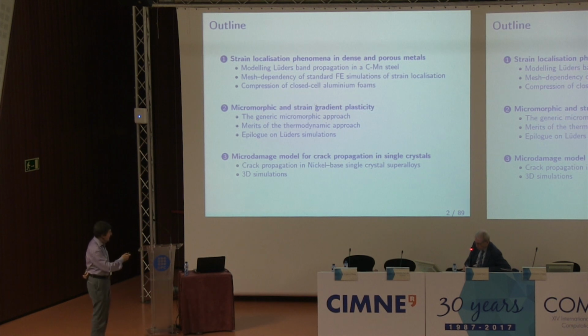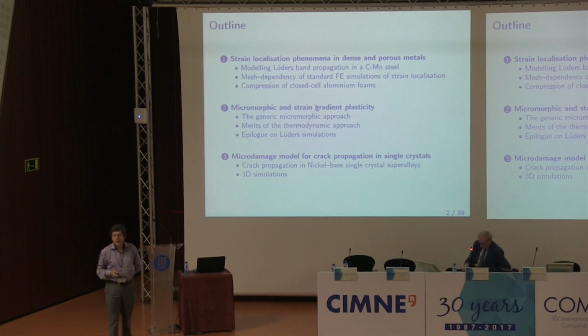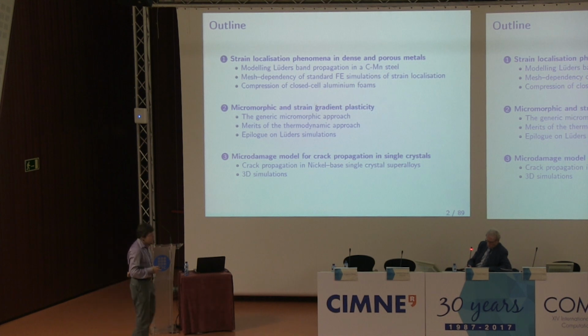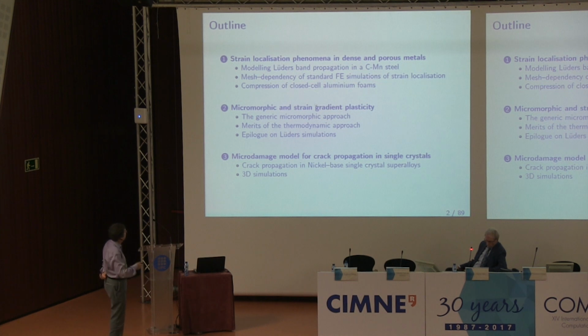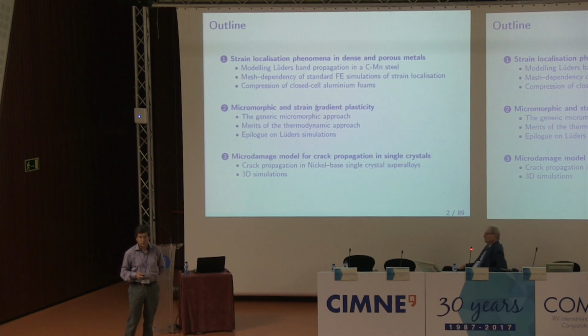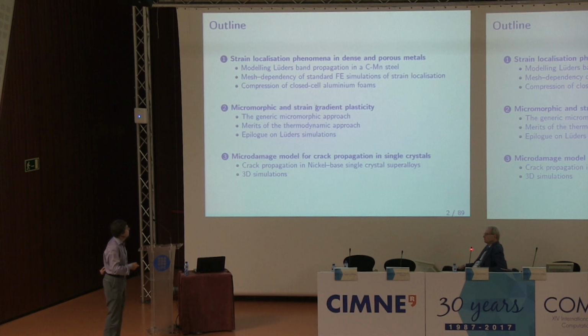I will apply this to strain localization for metals. Especially I will concentrate on the modeling of the propagation of Luders bands in steel. Then the last part will be dedicated to damage, which I call the micro-damage model, because it is based on this micromorphic approach. We will simulate the propagation of cracks in single crystals, also with a view to application in nickel-based superalloys.